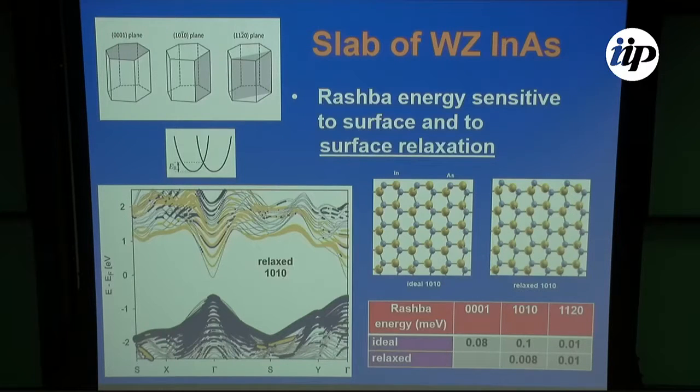A huge difference. So this Rashba is so sensitive to whatever you do in the sample. I know, if a wind blows over your sample, you will get a different Rashba, sort of like a butterfly effect, but it's really very sensitive. It's astonishing. So at the end, this DFT maybe will give experimentalists some benchmark, but at the end you just have to figure out the Rashba for yourself, what it would be. We are still working on it.